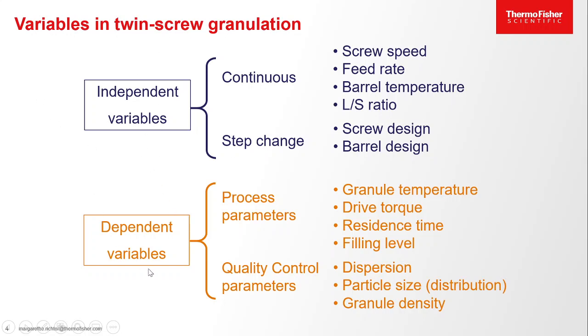Depending on these changes, you'll get results. And these are basically granule temperature, so the temperature will change based on all these settings. The drive torque, so how much does the machine actually have to work to perform the granulation, this will change. Also the residence time of your material within the granulator and the filling level inside the granulator. A twin screw process is never completely filled up, but it has always some void volume, and this of course changes. And then you get, of course, quality control parameters such as dispersion, so how well does the material disperse, how big are the granules, so granule size and distribution changes, and also the granule density.